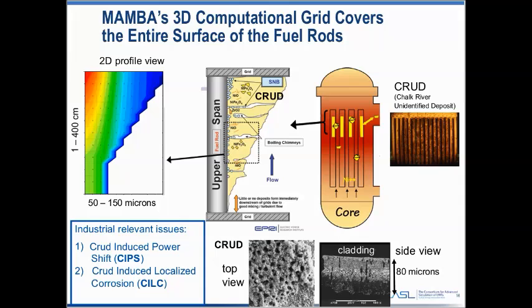On the middle left is a view of the computational mesh used by MAMBA. We grid up the CRUD layer. The vertical axis is the axial height, and the horizontal scale is the radial distance away from the cladding surface in microns. That shows a picture of the CRUD, which corresponds to the yellow layer in the middle figure. As Jeff mentioned, we want to address the industrial relevant issues, namely Crud Induced Power Shift, CIPS, and Crud Induced Localized Corrosion.